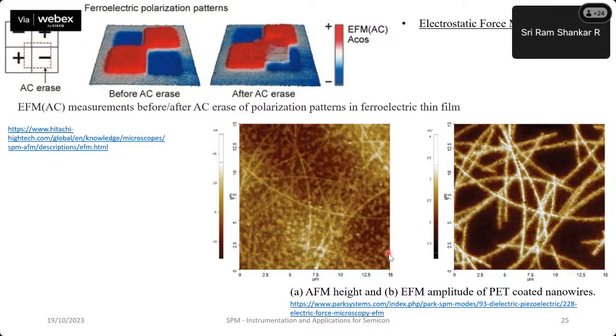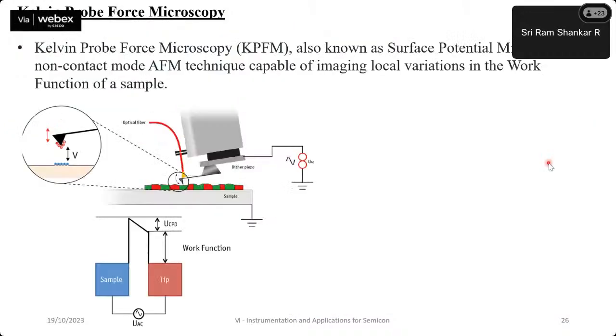So this is an example of nanowires that are coated with a certain material, placed on a substrate. If you look at just the topography image, it is very hard for you to differentiate between which is the substrate and which is the nanowire. However, with this EFM, electrostatic force microscopy, you are able to clearly distinguish between the nanowires and the substrate. There's one more technique called Kelvin probe force microscopy, with which you are able to characterize the difference in work functions between the material of the tip and the material of the sample. What can it be used for?